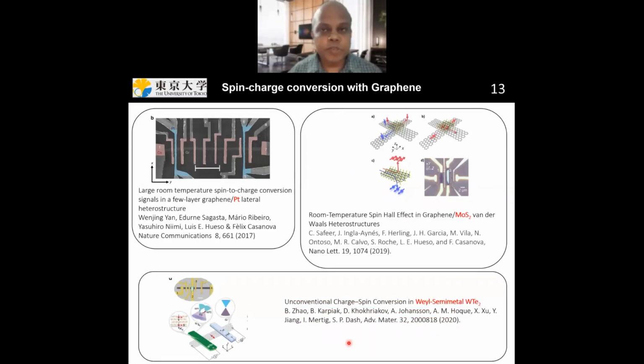For example, in the spin charge conversion community, graphene spin transport is now the most favored material for non-local spin valve devices compared to the previous generation of copper and aluminum. This is one example where the Felix Casanova group, in Spain, could measure spin Hall effect in platinum at room temperature using a graphene spin transport channel. In the same group, they also use 2D materials, for example MoS2, to study spin Hall effect and interface effects. And people are now using this kind of devices to study spin charge conversion in quantum materials, for example Weyl semimetal tungsten telluride. This result is from Saroj Dash group in Chalmers.